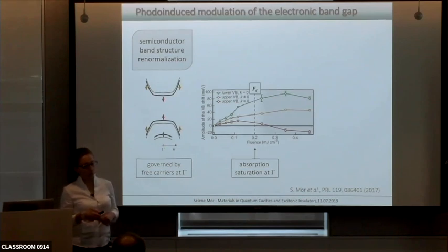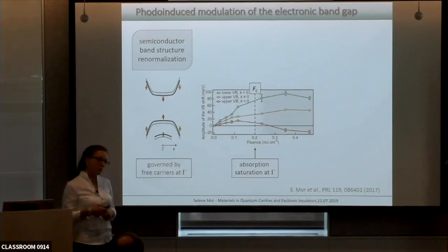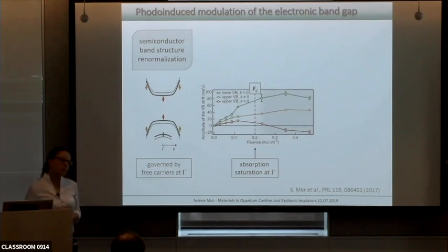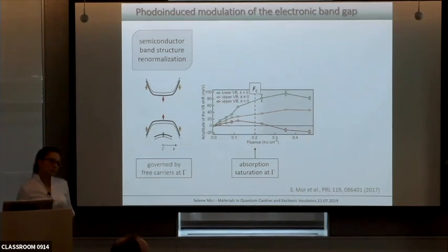For example, for the interpretation of the band gap renormalization, you say that it's immediate within the pulse, which is something that in the 1980s people were reporting in semiconductor physics: they were pumping, and because of the change in the exchange and correlation potential, people were seeing band gap renormalization. But in that case, time zero was set at the beginning of the trace. Here, if you look at your traces, there's a rise time.